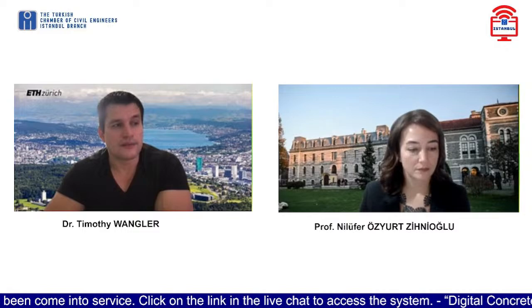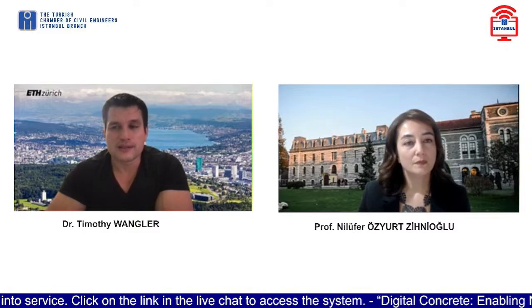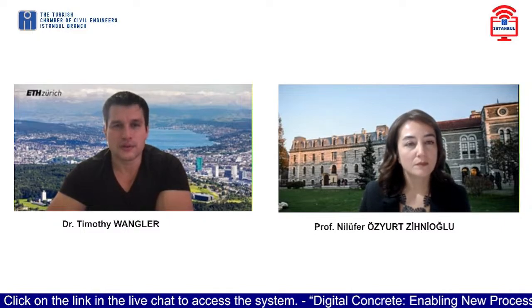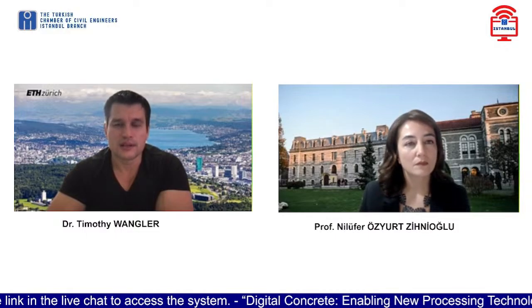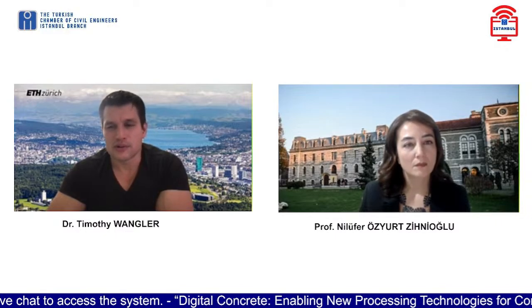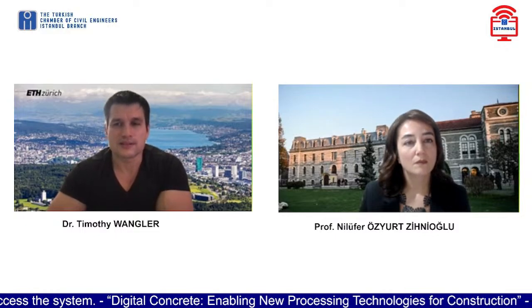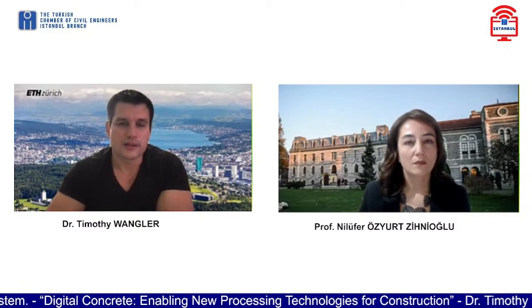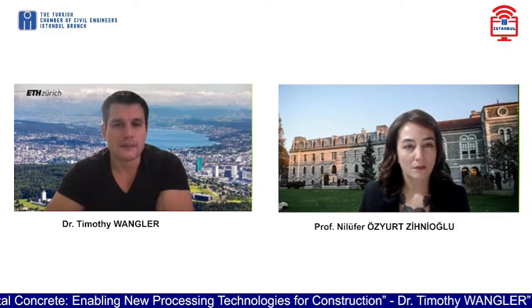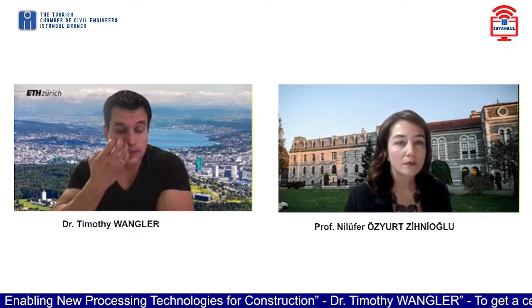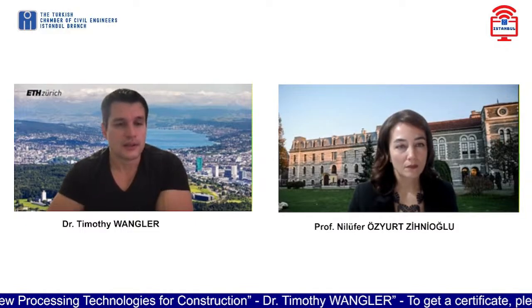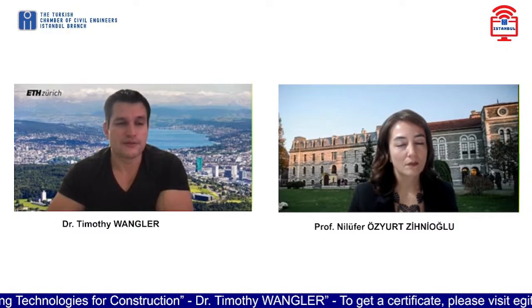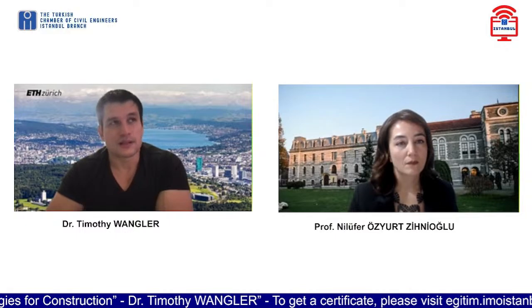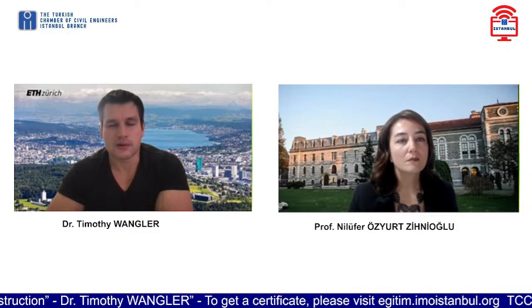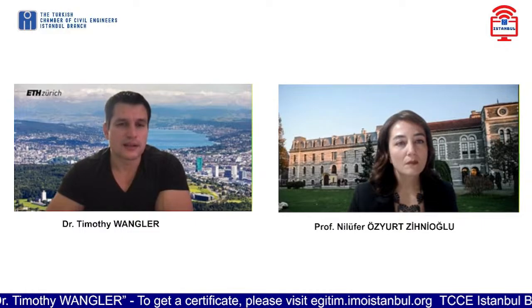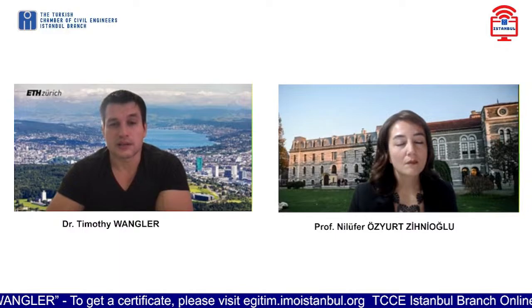Now, to answer your question, if it can be used in terms of accelerating buildability, I can't say for sure, but I don't think so, because carbonation is a diffusion limited process. And it's of course accelerated, very often in a prefabrication context, in CO2 chambers. So you'd have to be printing inside one of these chambers, and then you're still limited by diffusion, and the diffusion time, of course, increases by a factor of 4 if you double the diffusion length. So in terms of during the process, which generally takes, those columns were printed in 2 or 3 hours each, I don't think that it can help much. But I would have to actually check the numbers to be sure.